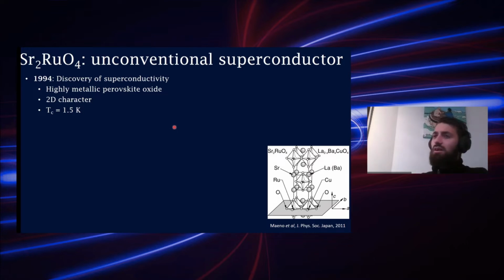It is a perovskite oxide that is isostructural to LSCO, and it has a highly 2D character. Actually, the superconductivity in this material was found while looking for other high TC materials. However, it is not a high TC; it has a very low TC of only 1.5 kelvin.